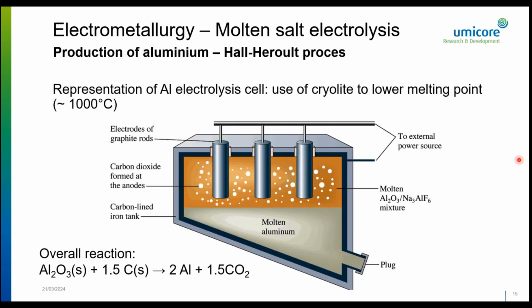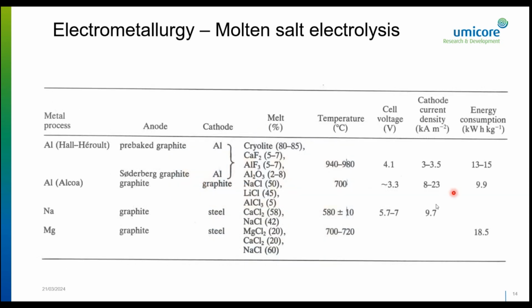Just to give you some examples, this is, for instance, the Hall-Héroult process, which is used to produce aluminum. So this is an electrolysis reactor using the fused salt. And what you have here is you produce molten aluminum at the cathode, and the counter reaction at the anode is actually oxidation of carbon anodes to CO2. So that's the counter reaction that happens. You can see here the total reaction equation. So that is aluminum production. All aluminum in the world is produced in this way. It's a very energy intensive process. Here you have the energy consumption indicated. So it's quite energy intensive, above 10 kilowatt hours per kilogram.